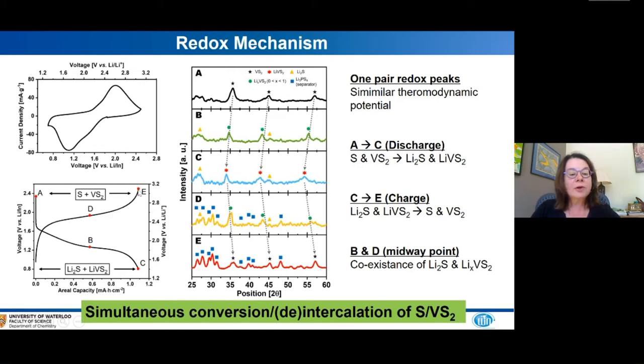At the top of charge, the X-ray diffraction data shown here on the right suggested we have a combination of sulfur and VS2, whereas on full discharge we have a combination of Li2S from the reduction of the sulfur and LiVS2 from exchange of the lithium incorporation into the VS2 layer. These diffraction patterns taken at points A, B, C, D and E all correspond to these points in the profile on the left.